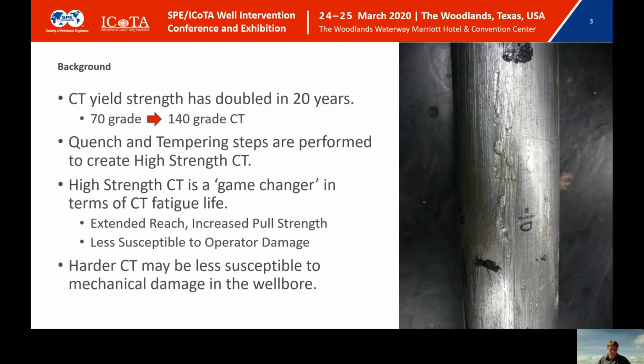The advancements in coil tubing metallurgy in the past 10 years have been absolutely amazing. The standard of the art used to be 70 grade coil tubing, and now 140 grade is commercially available. The big game changer has been quench and tempering coil. This has extended fatigue life. It's increased the hardness of the pipe, which in theory makes it less susceptible to damage in the wellbore. And given the additional strength of coil, it's less susceptible to operator damage such as overpull.